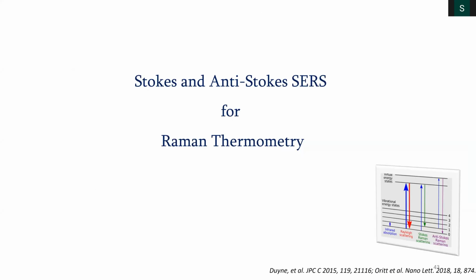So how do I measure the surface of the gold nanoparticles? You cannot use a thermometer, right? Because you are at the nanoscale. This is a very nice technique called Raman thermometry, where you use the ratio of Stokes and anti-Stokes lines. If you look here,